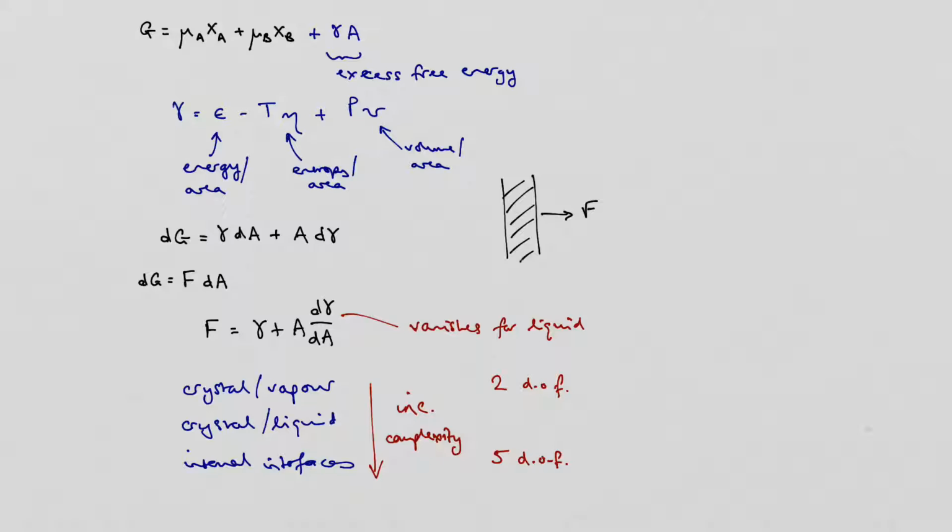Yeah? And it's because the surfaces just make a contribution which is proportional to 1 over the number of atoms, let's say 1 over the number of atoms to the 2/3 or something like that. As n gets very large, that contribution just gets very, very small.